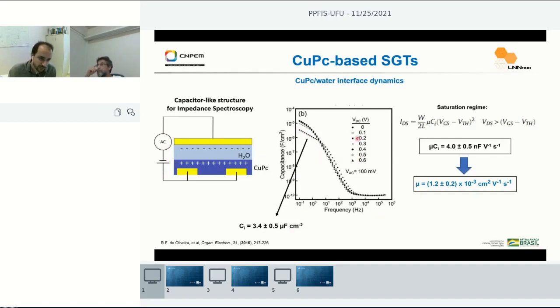And by superimposing a DC bias here, what we see is an increase of capacitance at low frequencies. So by using these values, now we can calculate and extract the mobility, allowing us to use this type of device for extracting important parameters that characterize the electrical properties of semiconductor thin films, more like organic semiconductors in this case.